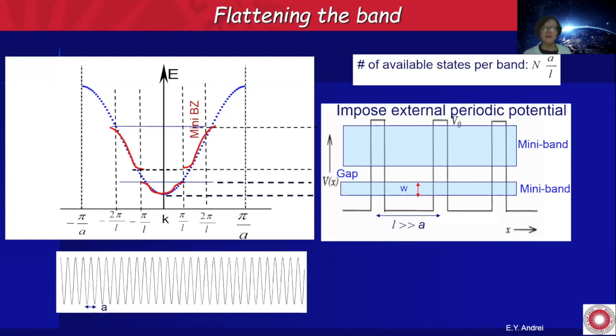So each one of these super periods becomes like an atom, and whenever the wavelength reaches the size of this super period, you get strong scattering. So basically, your band structure will have shrunk here and you'd have opened a gap at the new mini Brillouin zone. So now instead of putting n electrons in that to fill a band, now you're going to fill the band with n times the ratio of the lattice spacing to the super period to some power depending on the dimensionality. Squared, for example, if you're in 2 dimensions. So here is a very simple recipe to make flat bands.